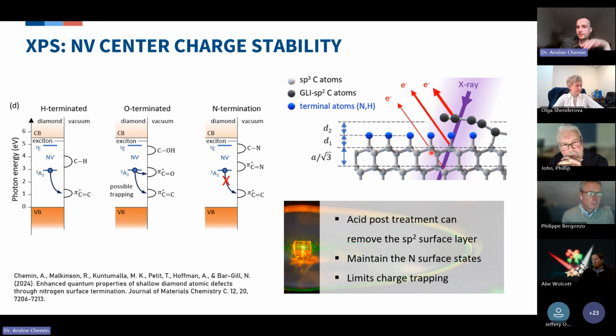Also, in the case of a very well nitrogenated surface, like in the case of the microwave, you don't really have surface sp2 reconstruction, because the sp2 is not at the surface, it's slightly above the surface. And so in this paper from last year or 2 years ago, we actually showed that nitrogen terminated diamond behaves better for the NV center.